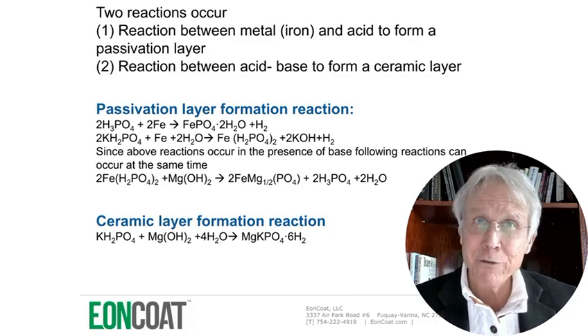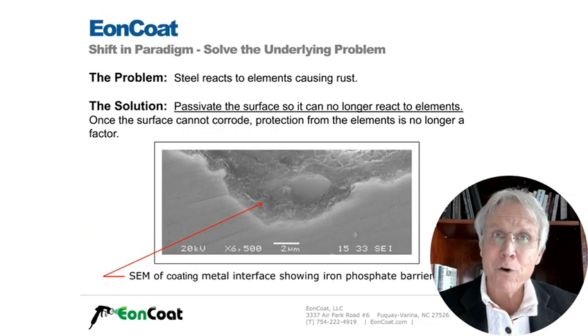This is the fundamental chemistry of the reactions that form the alloy layer and the ceramic layer which leaches phosphate. This is a photo taken by a scanning electron microscope which shows how the metal is actually alloyed. This picture is the width of one blast profile from peak to peak, about 20 microns wide.